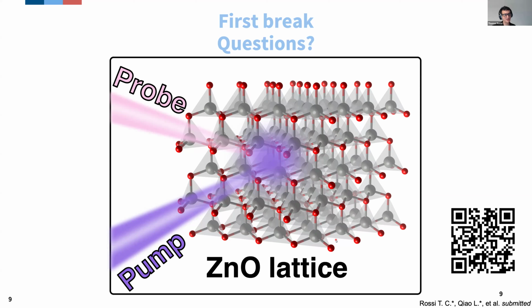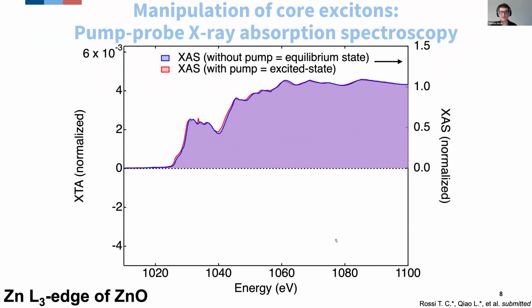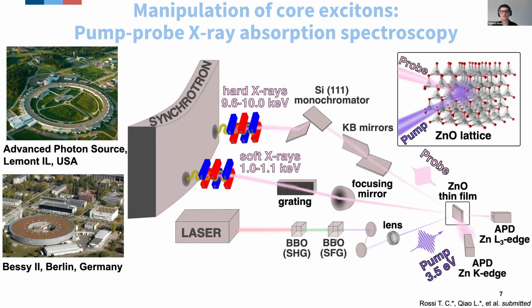Yeah, that's a great question. So there are two things you need to do. The first one is indeed, as you said, you need to make the footprint of the laser on the sample larger than the dimension of the footprint of the X-rays. That's typically something we do in pump-probe experiments, such that you probe only an excited volume of your sample. So you only see a part of the sample that has been excited by the laser pulse.